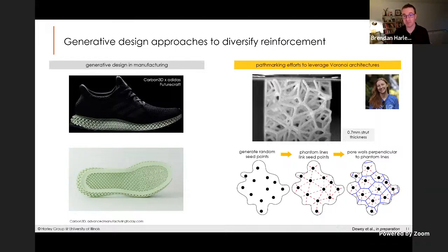We wanted something slightly different. We wanted a small, a medium, or a large size scaffold that could be cut down to a defined space in the operating room and have dependable properties. So what Marley developed was an approach using Voronoi foams. And Voronoi foams sound super fancy, but basically they're random three-dimensional structures where you take a 3D space you want to print something into, and you litter it with what's known as seed points. And the Voronoi foam is based on the number of seed points and the spacing between them. And you can print these out.